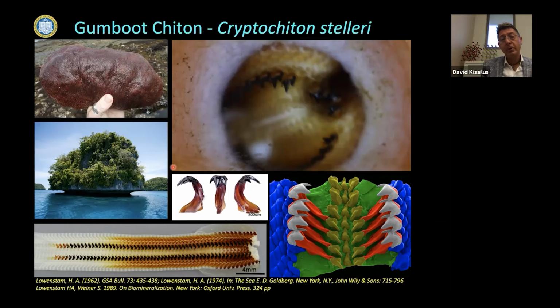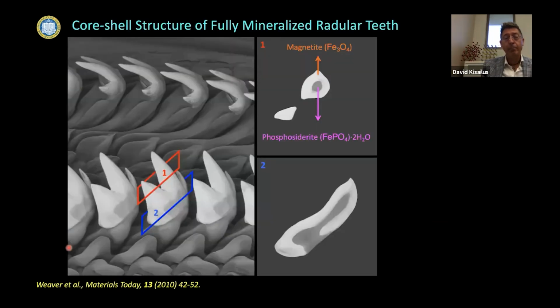But it gives us an opportunity to look and see, how does this mineralization actually occur? So the teeth themselves, just taking a cross-section through the teeth, they're tricuspid, and they have a core shell structure. The shell is actually made of magnetite, and the core is an iron phosphate called phosphosiderite. So much like human teeth with enamel and dentin, this is magnetite and phosphosiderite.